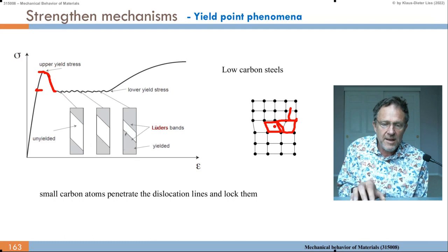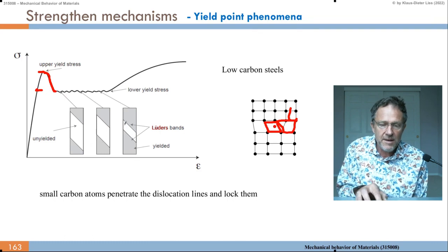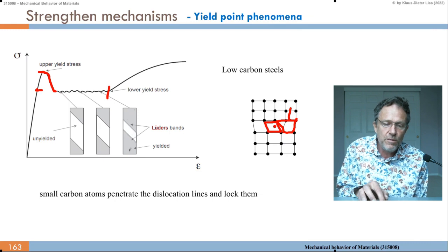So the Lüders band can nucleate anywhere, can nucleate at the borders, can nucleate in the center. But here we see this unyielded area becomes smaller and smaller, the unyielded volume, because I get work hardening in the already yielded gray areas. And that goes until here. That strain is when all this white area is consumed. Basically when the two gray areas touch each other, they meet each other. And then I do the normal work hardening.